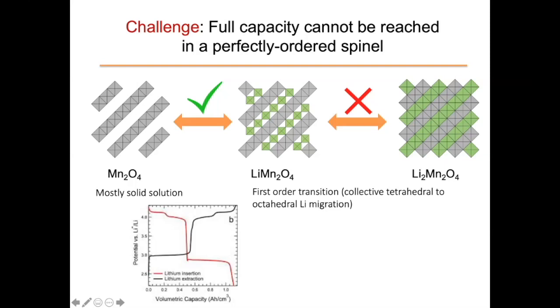What you really want to do is cycle it all the way from Mn2O4 to Li2Mn2O4, so you would have close to 300 milliamp hours per gram. But of course, as we all know, that doesn't work really well because this part is a first order phase transition, and you can see that from the flat voltage profile. A first order phase transition is bad because it occurs, by definition, inhomogeneously in a material. And therefore you get cracking, you get all kinds of negative effects on cycling.